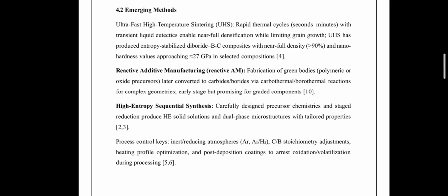Second one is high entropy sequential synthesis. High entropy sequential synthesis requires engineered precursor chemistry and staged reduction pathways to achieve a homogeneous solid solution. Sequential synthesis allows control over phase formation, enabling the production of single phase high entropy ceramics or dual phase microstructures with tailored thermomechanical properties.